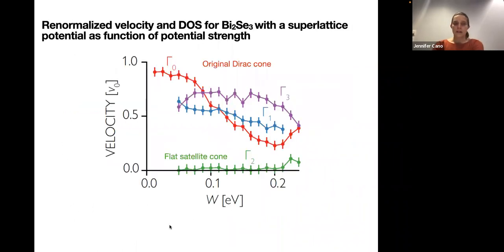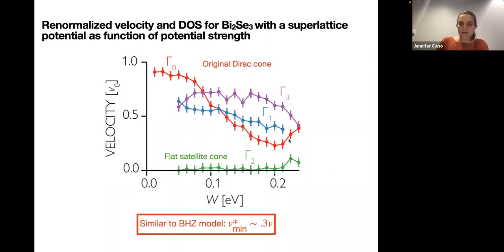So when we impose that periodic potential on the TI surface, this is again a plot of Dirac cone velocity versus potential strength, but now it has real units because we're thinking of a real material. You should look at this red curve. These red dots are again different numerical calculations, each occurring at a different strength of this potential. As we turn up the potential strength, the velocity of the Dirac cone dives down again. The interesting thing to me is that, similar to our toy model, it reaches a minimum, around 1/3 of its original value, and then it comes back up. So by applying the superlattice potential to the TI surface, the Dirac cone velocity can be significantly changed to roughly 1/3 of its original value.